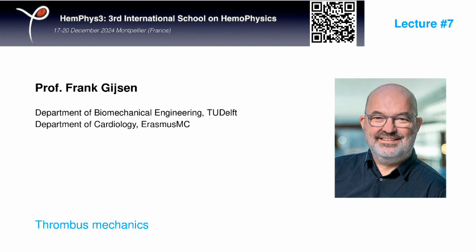So you need to characterize the behavior in tension, compression, and we just designed a device that we can also do shearing experiments on. I think the most important information that we are still missing, and which will be hard to quantify, is how they fail. Because that's something that happens during these processes all the time. We penetrate them, we break them, and then they fail, and we have very limited data on how that process actually is going on.